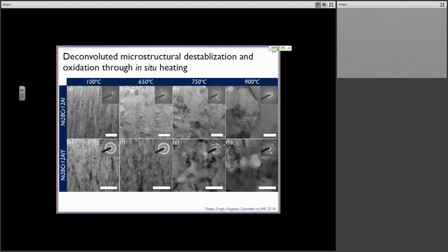We have relatively equiaxed grains already showing up. And you can see some of this is more obvious in the diffraction pattern, because down here in the yttrium-containing alloys, there's still ring patterns, which suggests that the grain size is very fine still. As we go to slightly higher temperatures, now, even in the yttrium case, we've started to create these equiaxed structures, and the grains are growing.